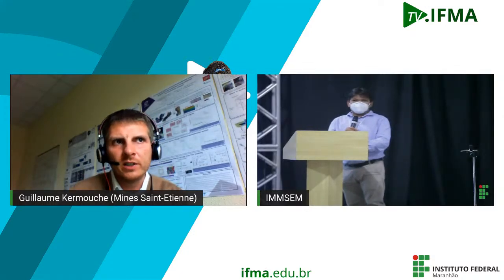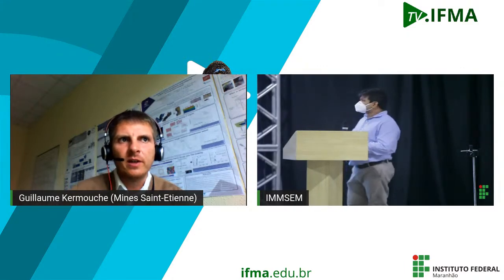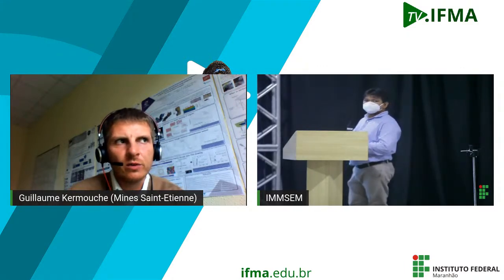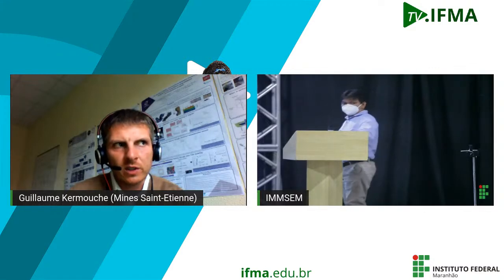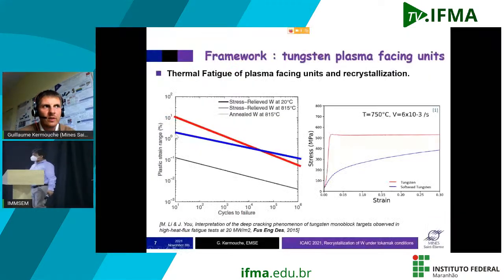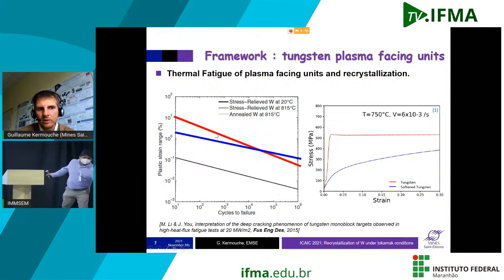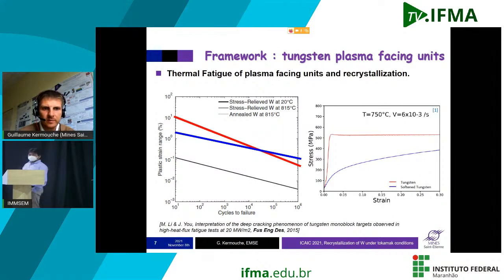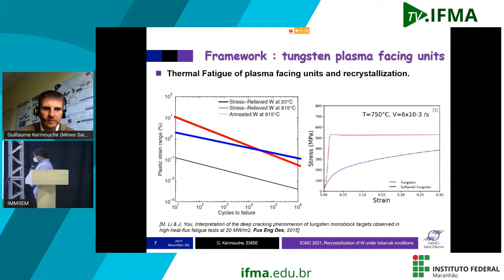Yeah, this is this slide. What you can see is that if you have a recrystallized tungsten, this is the blue curve. Finally, the fatigue curve is worse than the unrecrystallized fatigue curve. So this is the only material for which we get this kind of result. That was a bit surprising at first, because for most materials, this is the opposite. But in terms of hardness, this is like any material. The hardness decreases with the dislocation density. Thank you very much for your answer.